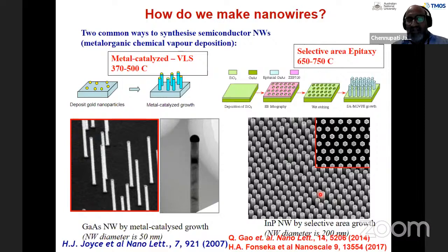This is the work of Dr. Qian Gao, who is a research engineer, and also Dr. Aruni Fonseka. Dr. Qian Gao is at BlueGlass in Sydney, a company, and Dr. Aruni Fonseka is at Warwick University in the UK. You can see that because we created ordered patterns of these structures, you can really get these beautiful ordered arrays here. You can also see beautiful hexagonal facets because these nanowires are growing along the 111 crystallographic orientation. That's the lowest surface energy orientation of these structures.